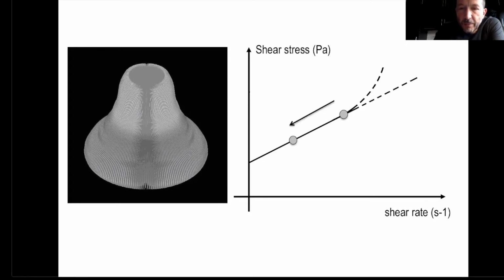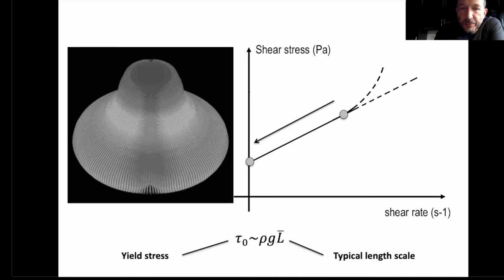So it starts to slump, and as it slumps, the typical length scale, which is here the height of the sample, decreases and the flow slows down. It slows down until the stresses induced by gravity inside the sample are equal to the yield stress. So we have here an illustration of this very basic relation between a length scale and a yield stress, and the explanation why this test is so efficient at capturing the yield stress or the consistency of a given cement-based material.